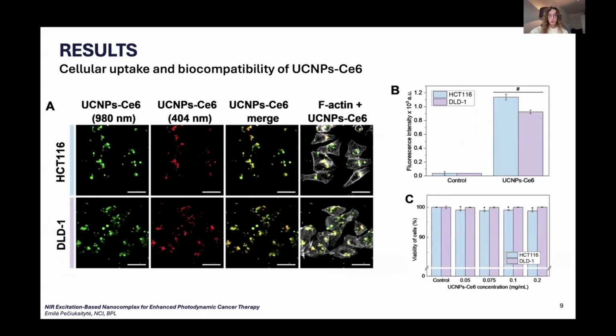Further on, to determine whether the nanocomplex can be used in cancer therapy, we first examined cellular uptake. After 24 hours of incubation with 2 human colon cancer cell lines, the complex was internalized and localized predominantly in the cytoplasm. And the overlap that you can see in the image between upconverting nanoparticles and chlorin e6 fluorescence only confirms that the complex remains intact and stable inside the cells. Flow cytometry in picture B shows that HCT 116 cells accumulated the complex 1.2 times more efficiently than the DLD1 cells, and importantly,